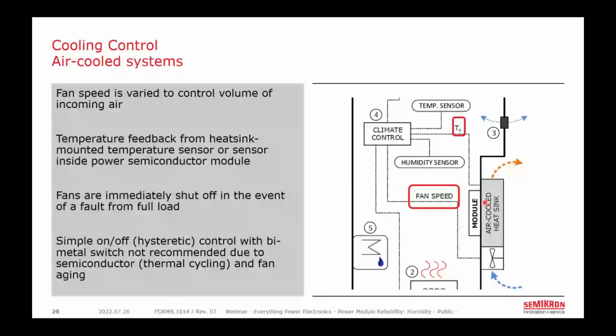With this setup, we can immediately reduce or stop the fan when there is a quick change in load and avoid that relative humidity overshoot we discussed earlier. And if we monitor the outside air temperature, we can also make sure that we're not drawing in very cold air, such that the heat sink itself is cooled below the dew point, where we can risk condensation. Of course, there are other considerations here, such as ensuring that you're not wearing the fan out, as in the case of simple on-off or bang-bang control with a thermostat.